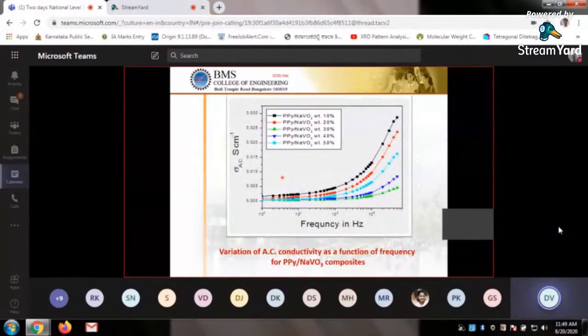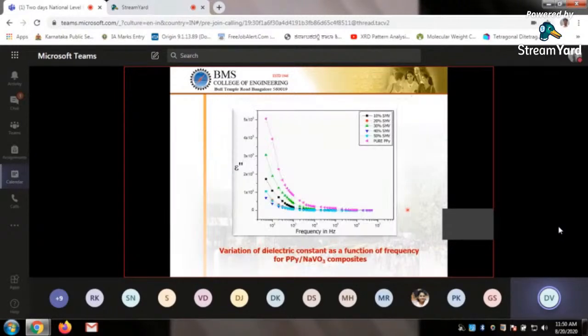So if you plot a graph between AC conductivity and frequency, again, how it varies with respect to frequency for our samples. As frequency increases, conductivity is a little bit constant till 10^5. Then as frequency increases further, the conductivity increases. So at higher frequencies, it gives you more conductivity. That's what we observed for all the composites. Okay. And again, dielectric constant.